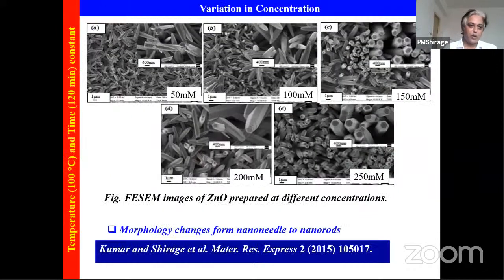Okay, so if we keep temperature around 100 degrees centigrade, we have 4 parameters. I will only talk about the 3 parameters now. Doping is not concerned here; I'll come to doping later. So we are keeping temperature around 100 degrees centigrade and time for 2 hours. Then the parameter left is concentration, so we have to change the concentration. I utilized 50 millimolar, 100 millimolar, 150 millimolar, 200 millimolar, and 250 millimolar.